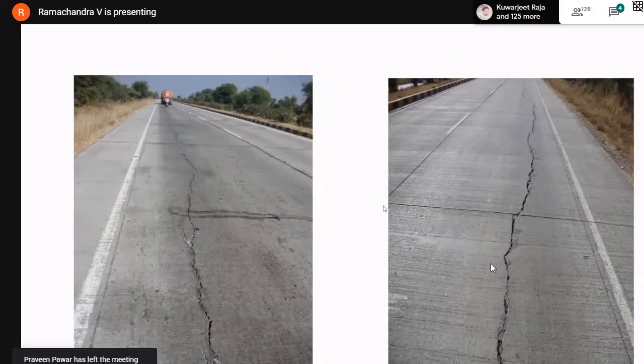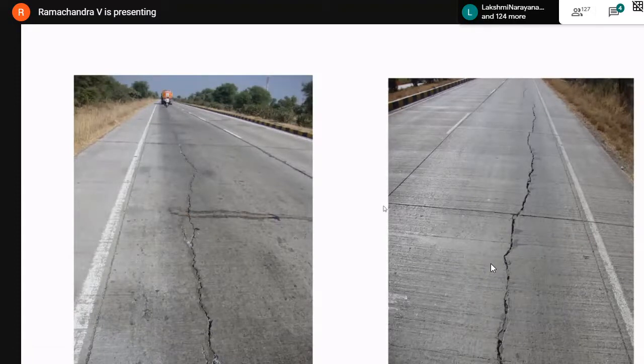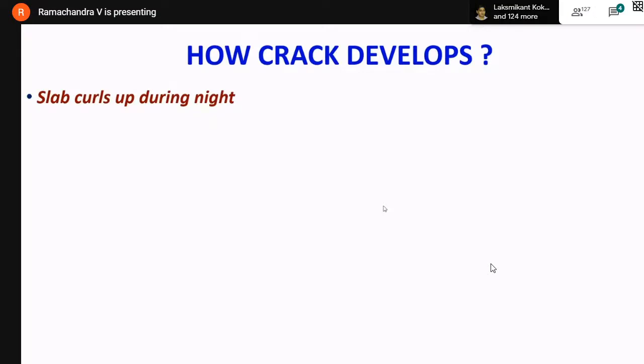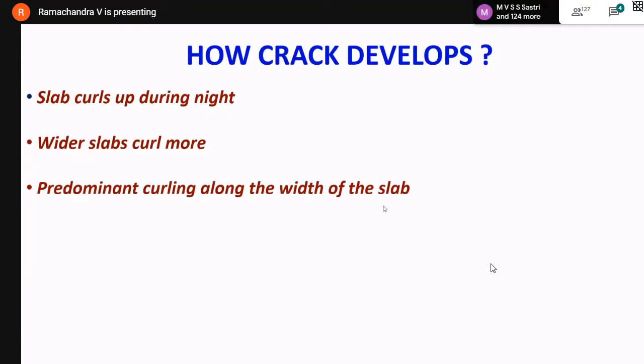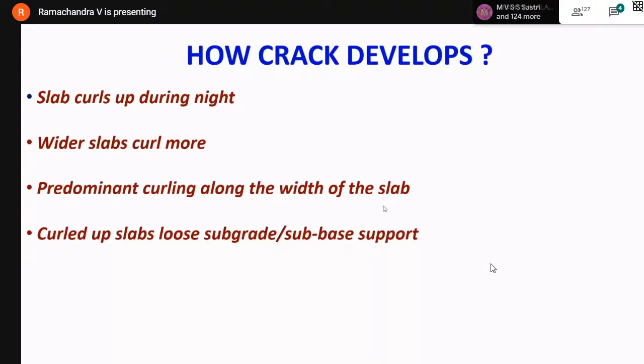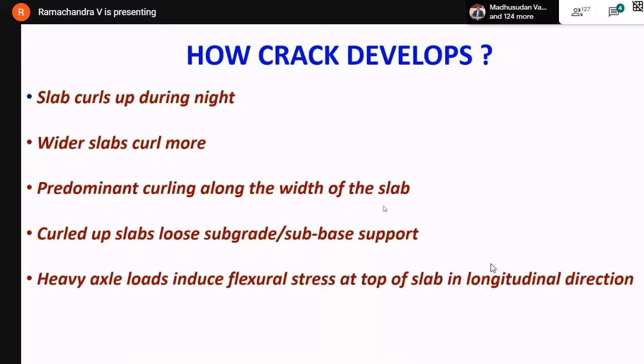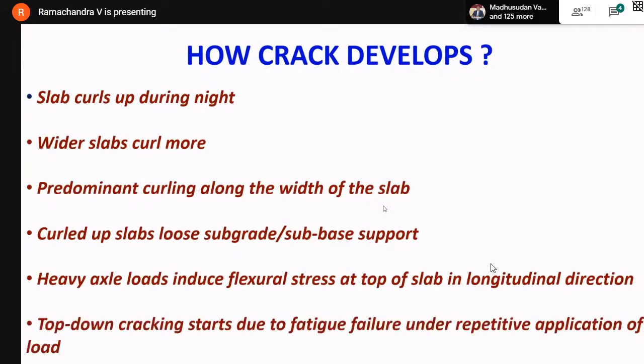This is a structural crack. Now we are talking of concrete roads, not white topping. In white topping, it is 1 meter by 1 meter spacing. Here it is 3.5 meter by 4.5 meter, that is the panel size. Why do these cracks appear? It is because the slabs curl up during night, and wider slabs curl more, and predominant curling happens along the width of the slab. In the curled up slabs, with loose subgrade/sub-base support, heavy axle loads induce flexural stress at the top of the slab in the longitudinal direction. This also happens due to top-down cracking that starts due to fatigue failure under repetitive loading.